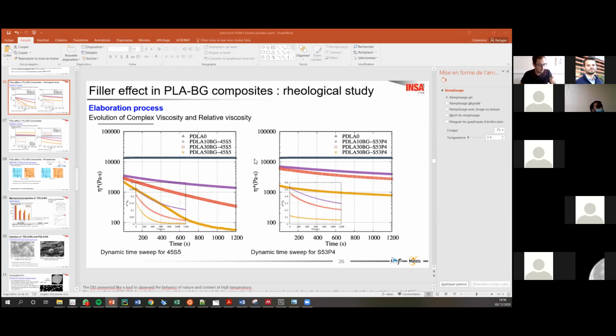I haven't tried it already, so I cannot assure you of that. My feeling is that if we increase the shear rate or the strain, we will accelerate this degradation, but I don't know if we could see it in rheology. Yeah, with this I completely agree. Indeed, you could change the conformation of the chains or the filler distribution, so you see a lower viscosity, not necessarily related to the degradation. I fully agree.